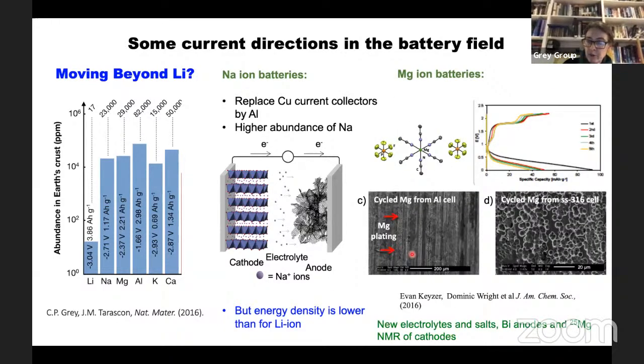This is some examples of work with myself and Professor Dominic Wright, and former PhD student Evan, who was looking at this issue of how do you strip and plate magnesium. Evan synthesized a new version of salt. The typical salt in a lithium-ion battery is LiPF6. What was surprising was that no one had made the magnesium PF6 before. Dominic Wright and Evan were able to do this, and then we were able to make an electrolyte and look at the stripping and plating.